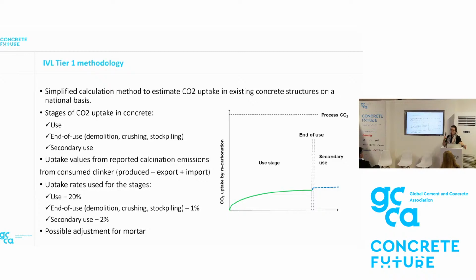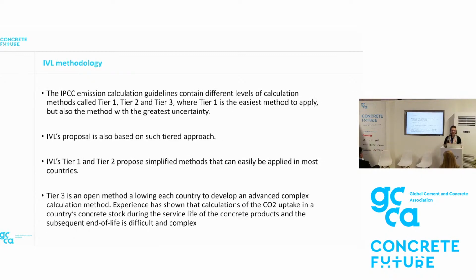And then there is also an adjustment that is foreseen for mortar, even in the tier 1. You may have seen, for those who are used to it, many Chinese studies, for example, that claim a much higher recarbonation potential than the 20%. There are different reasons for it, and those studies were considered here. But one of the main reasons for the difference is a much higher mortar assumption in China than elsewhere in the world. So that's the reason for the difference. But this is what can be claimed, or assessed. So a very conservative assumption. And then we have a tier 2 and tier 3.